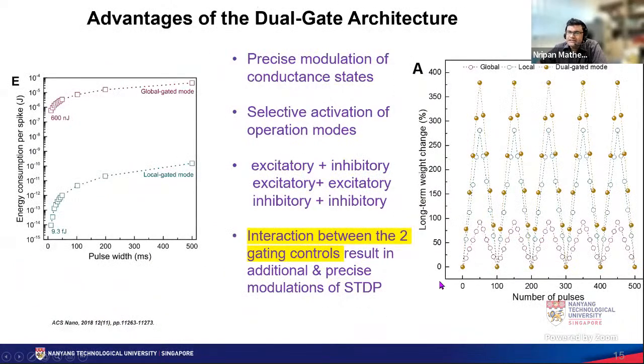Based on that, we are able to modulate the conductance states of the indium tungsten oxide. The global mode is the electronic mode that is shown over here, and that is limited. The local ionotronic mode can actually have much more long-term weight change, while the dual gated mode, where we apply both of them, adds on top of each other and gives us the largest weight change.